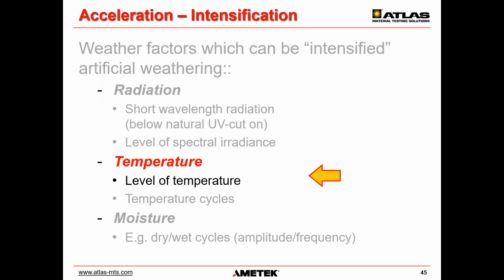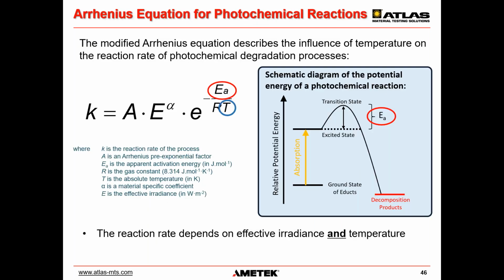For temperatures, we can possibly raise the temperature to higher levels in an effort to increase degradation rates, especially for physical degradation mechanisms. We can run tests that employ temperature cycling. A rule of thumb in basic chemistry class is that reaction rate doubles for 10 degrees Celsius rise in temperature. Rule of thumb. However, that only applies to some specific chemistry in solutions and is not true for the solid state materials we mostly deal with. The rule is derived from the more general Arrhenius equation, where K is the rate of the chemical reaction.